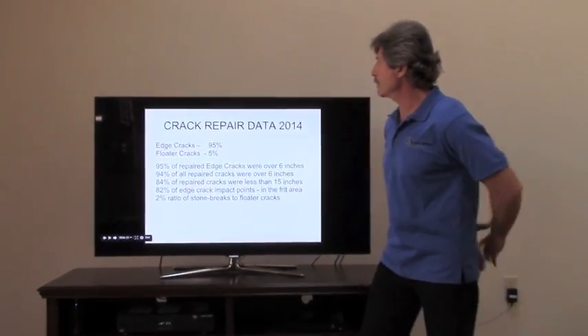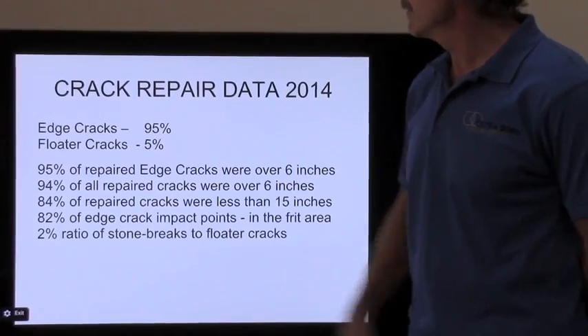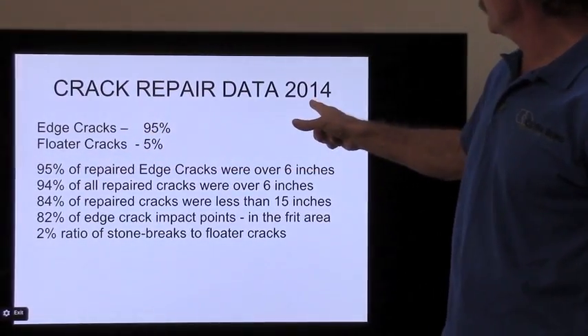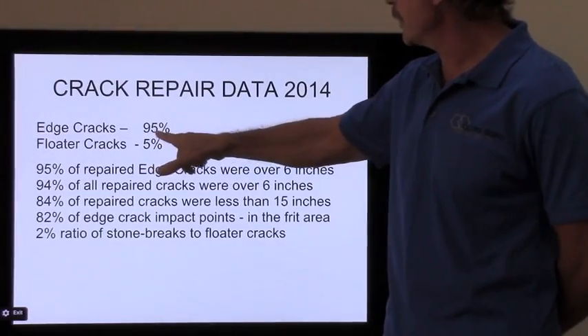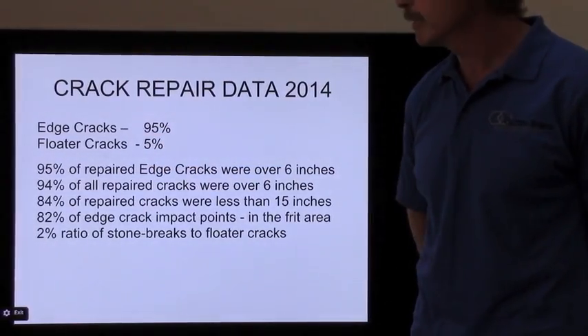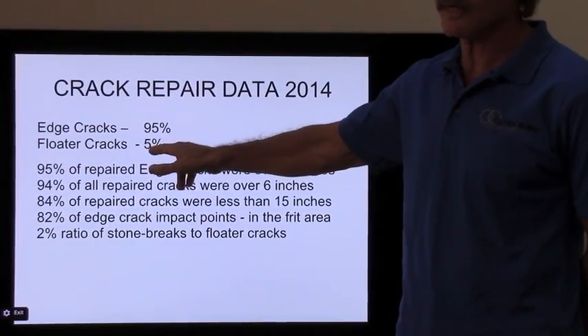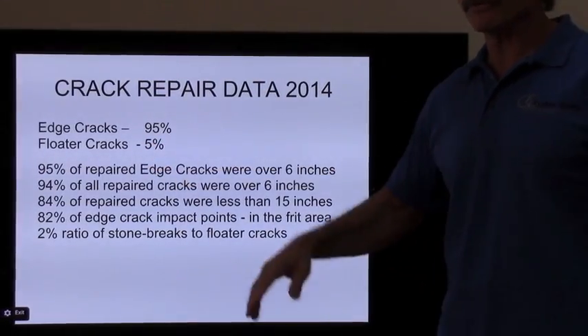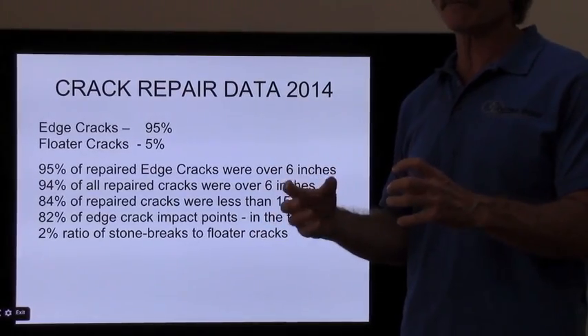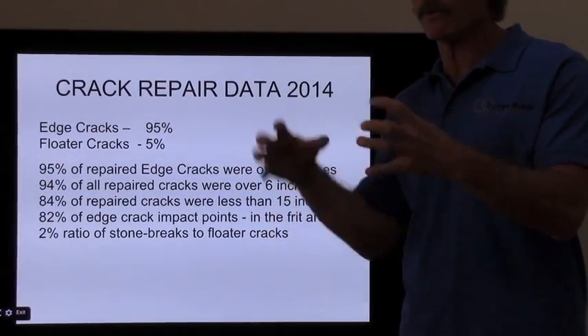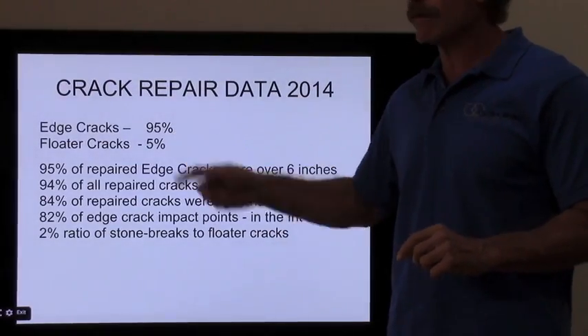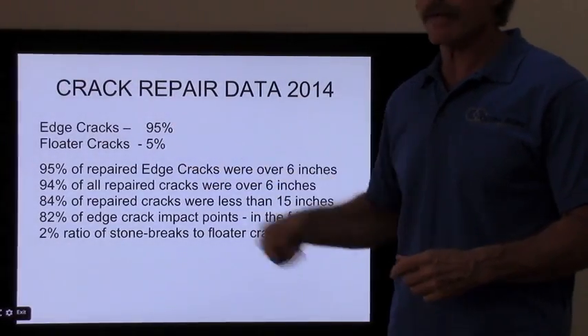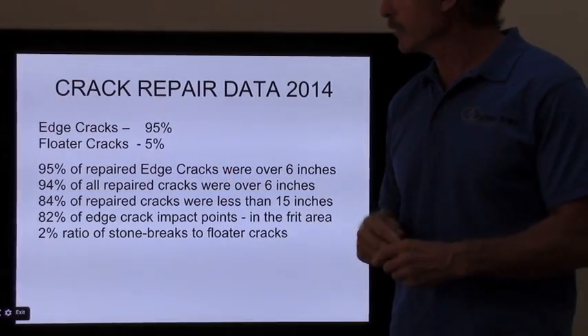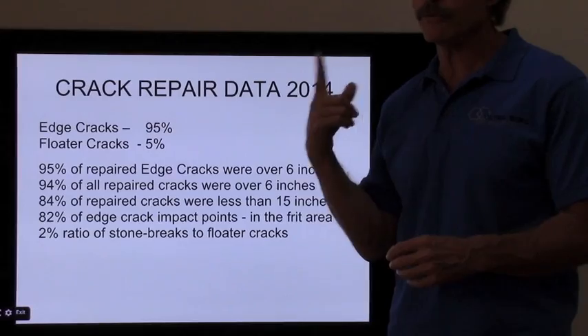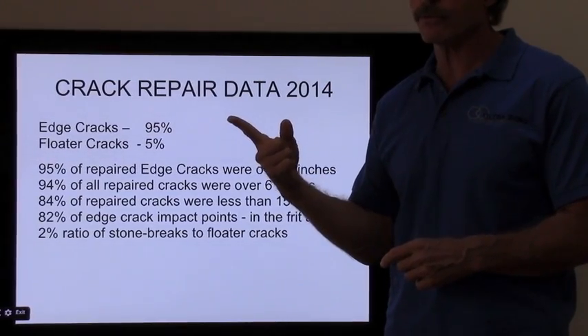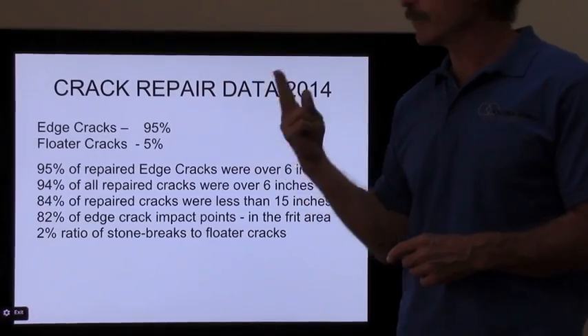Here's some data on the crack repairs, edge cracks and floater cracks. The edge crack represents, this one was recent, 2014. Our data showed edge cracks were 95% of the cracks that we repaired. And the floater crack, which is a stone break that cracks out, were only 5%. Remember, I told you a stone break has that PVB bond, the 3,000 PSI bond holding it together. So they don't crack out that often. Whereas the edge crack, when that fractures, it cracks immediately. See, when a stone hits a windshield, it does one of two things. It causes an edge crack if it hits the weak spot area, or it causes a stone break if it hits in the middle.